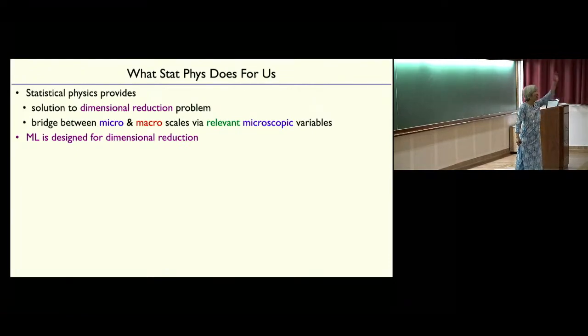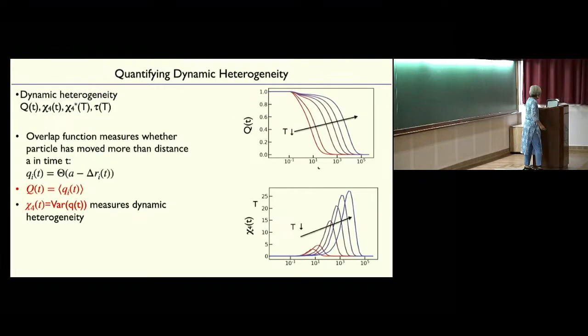What is typically the functional form of this relaxation time? The functional form of the relaxation time on temperature is that super-Arrhenius dependence that I was showing you before. The plot you showed, was that a linear-log plot? Yeah, this is linear-log. This is a log scale in time, and roughly equally spaced, not equally spaced, temperatures. The temperatures at which we measure are getting closer together as we get closer to the glass transition.